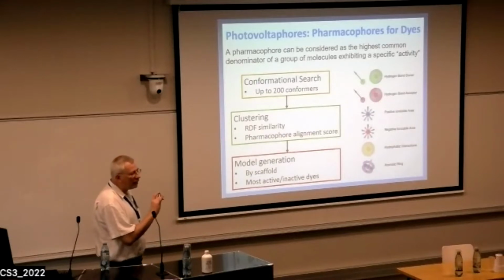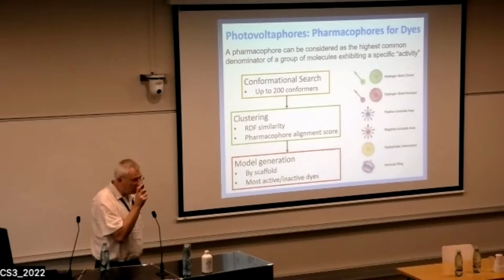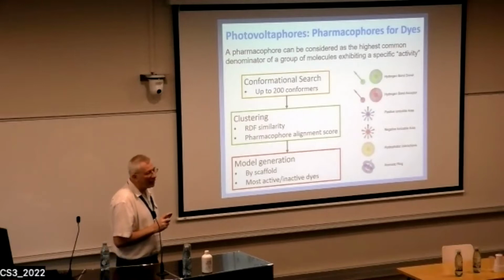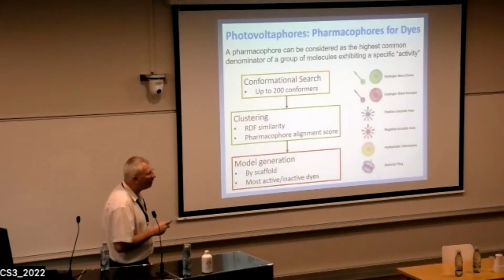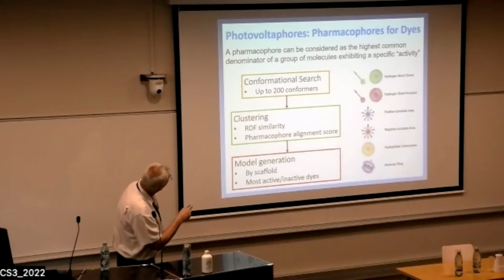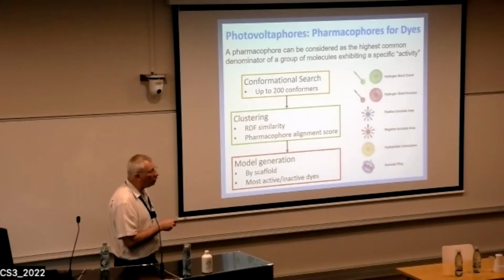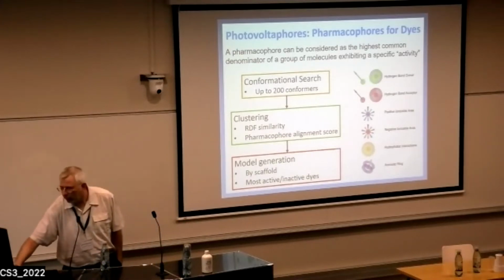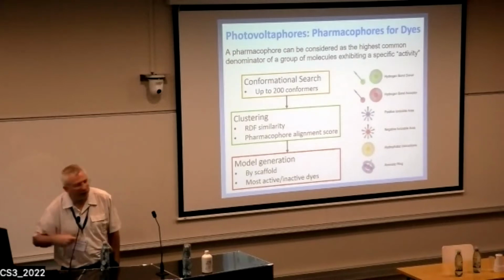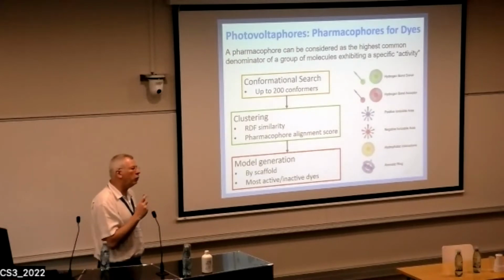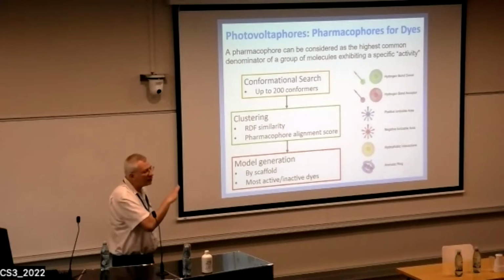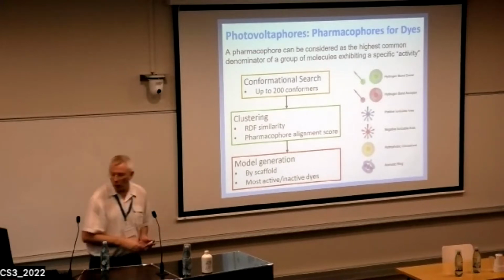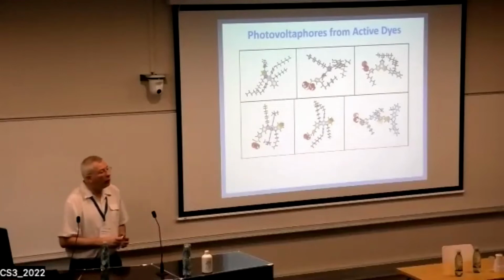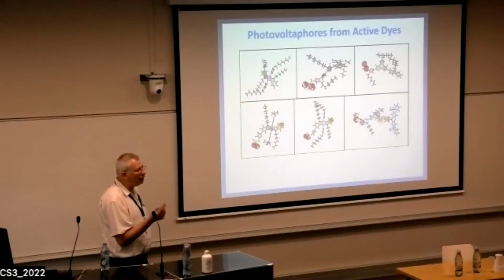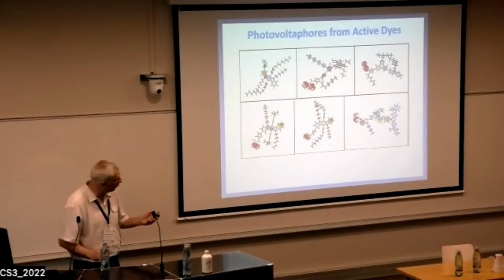Anyway, we did a classical pharmacophore work using LigandScout. So this is, I think, a nice extension of the program. We did a conformational search, we did clustering, we generated models for each of the scaffolds, and we also looked at the most active dyes and least active dyes across all scaffolds and tried to generate models. We generated models for the highly active or the better dyes. We also generated other models, and I'm showing some of them here.